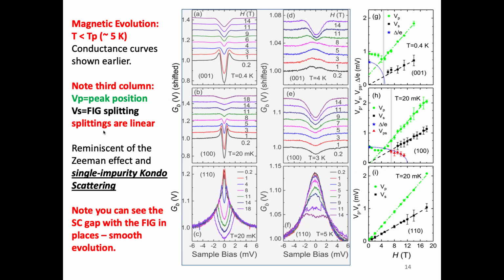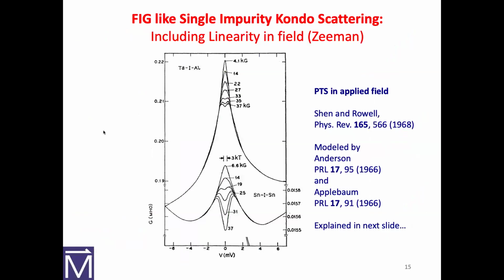So all we have here is that as a function of field, as we expect, the superconducting gap goes away in the way we would expect. Also with field, we find a splitting that continues to a field way beyond the superconducting temperature, so it's not due to superconductivity, and it grows linearly. And Anderson said, Zeeman, and that's why we reached into Shen and Rowell's paper.